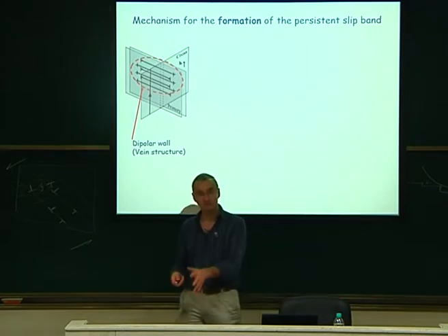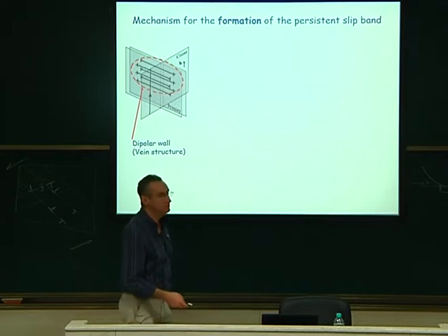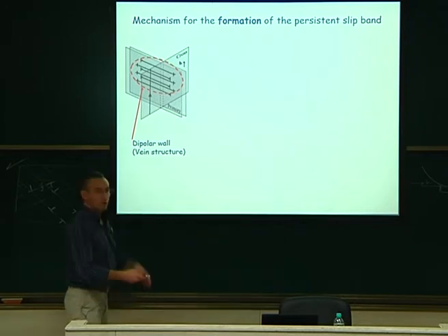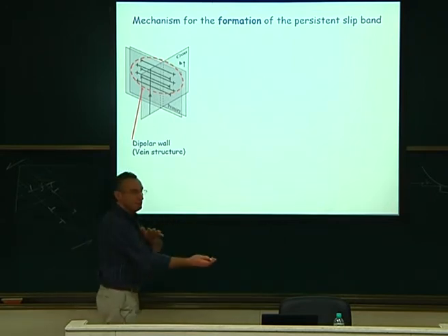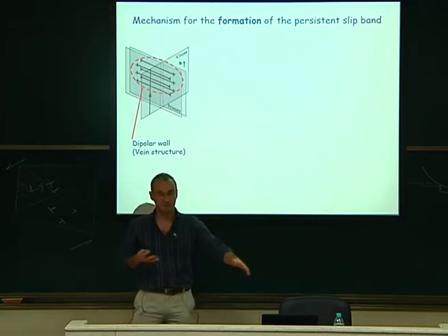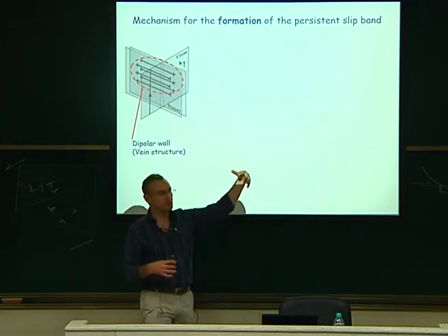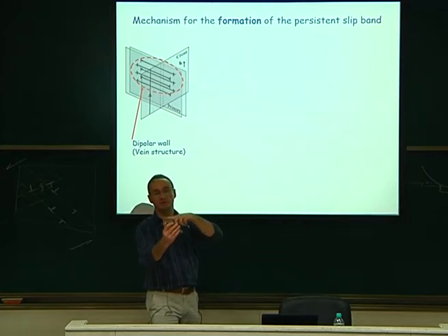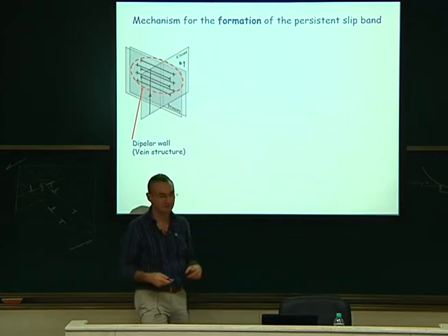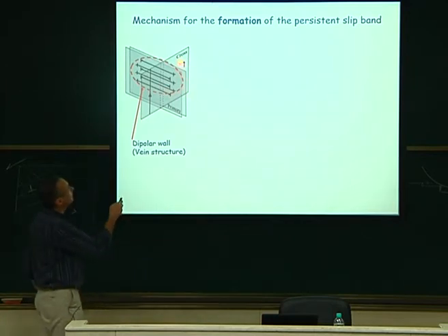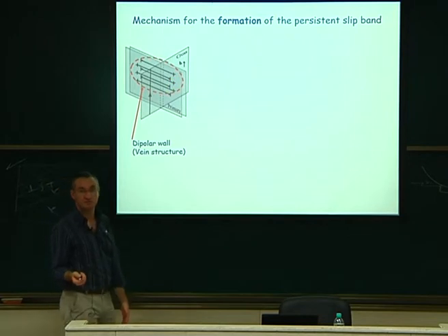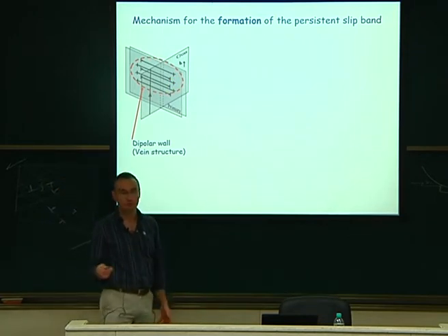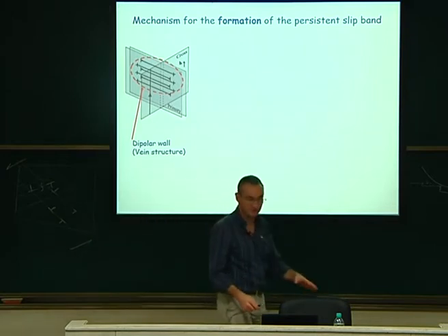Now, how does this band form? And this is, I think, the most important information you will get today. Because of the fatigue test, you are moving dislocations up and down, and it's reversed. So if you have a source here, another source there, they can very easily meet or glide in very close vicinity. Then you can form what we call a vein structure. You have positive and negative dislocations. This is dipoles. The dipoles you computed in the tutorial are located very frequently in the fatigue simulation.